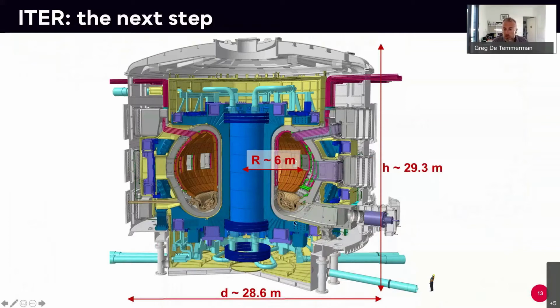And unfortunately, the reason for it to be almost true is because fusion is incredibly hard. And so far, we never managed to create energy from fusion. So we managed to have fusion reactions, to confine a plasma at really high temperatures. We even went up to 500 million degrees in the 90s. So we can reach all the conditions, but not at one place at one time, so that we never managed to create energy with fusion.